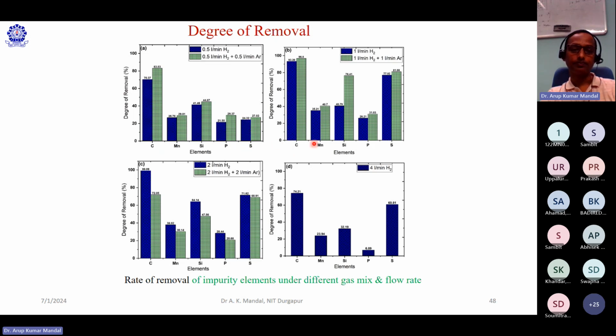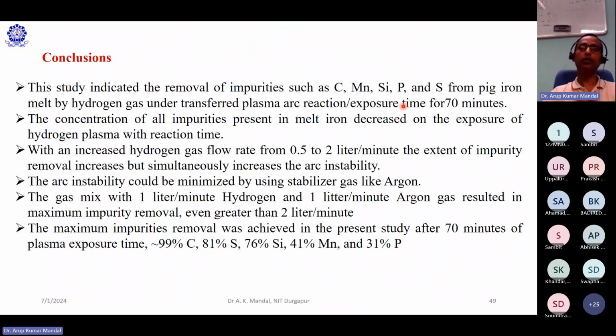So you can see here, the sulfur removal is optimum in the case of the 1 liter hydrogen plus 1 liter argon combination. Actually, what is the requirement of argon? It stabilizes the arc. When you increase the hydrogen content, obviously the reaction will increase, but arc instability will also occur. But if you give some stabilizing gas like argon, what will happen? The arc will be stabilized. Continuous arc will be there.